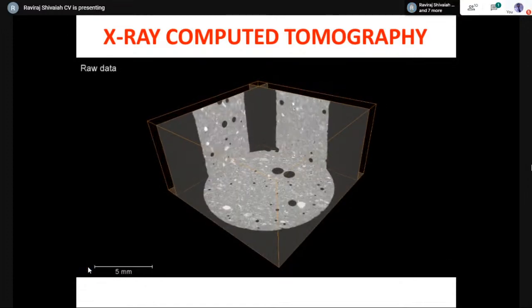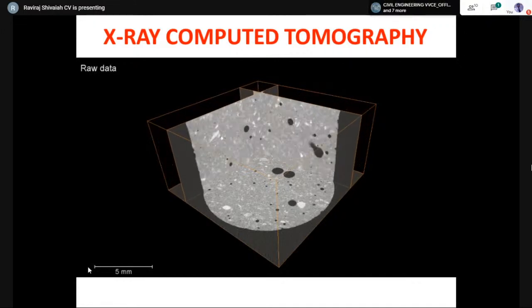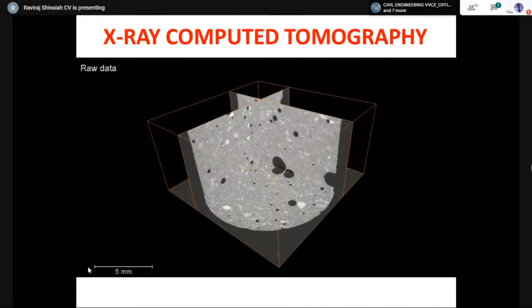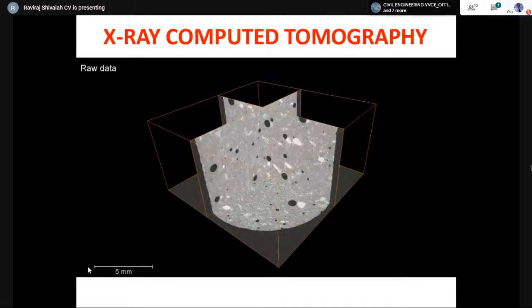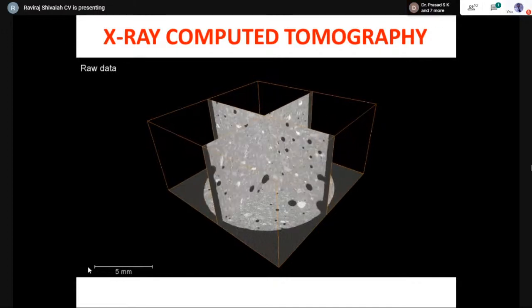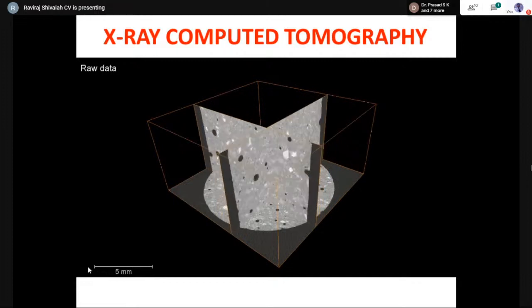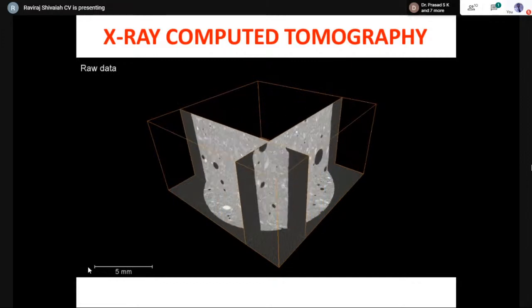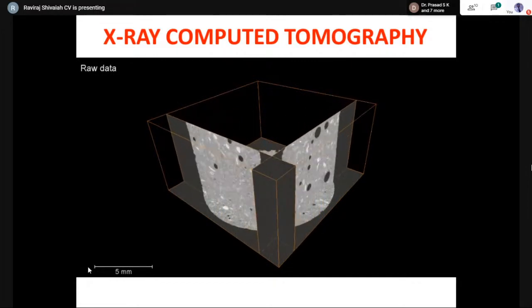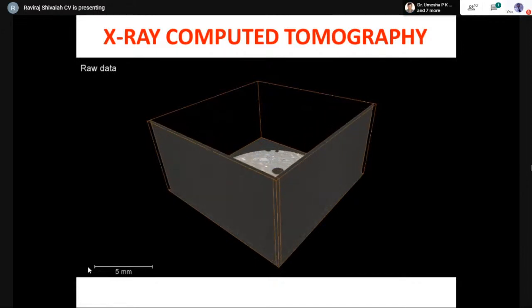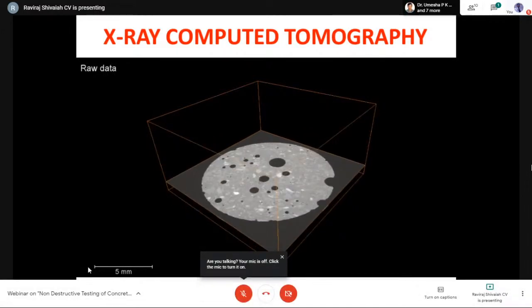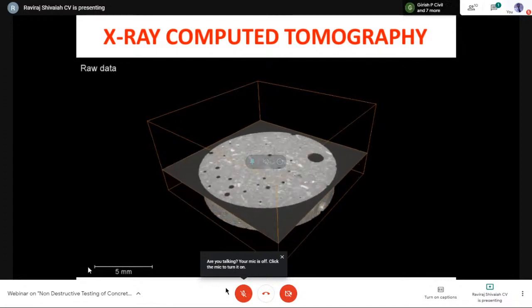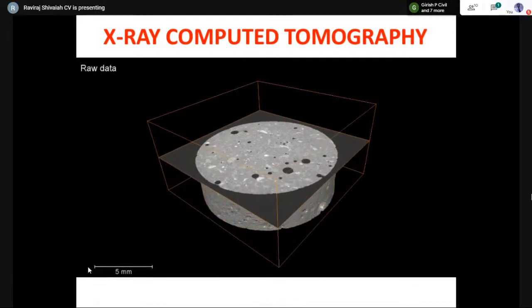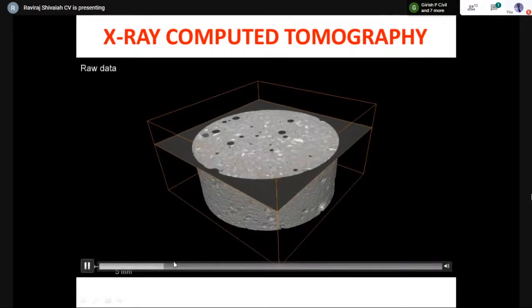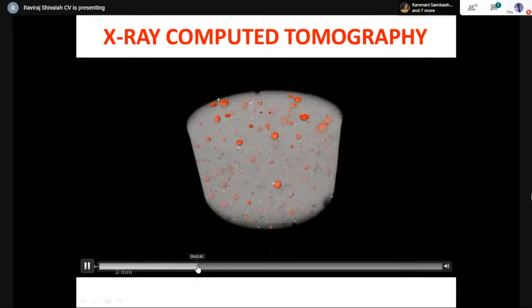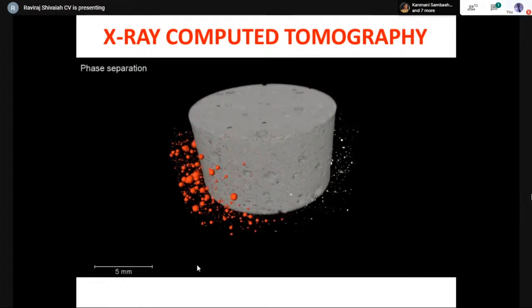So we have a simple concrete cylinder here where you are trying to move the slice in the X direction and Y direction, and you can clearly see the voids, the inclusions that we have, like the matrix, and the cement matrix and cement paste itself. So these are slices taken in X and Y direction. This is a slice taken in the Z direction. So those are the perpendicular directions. You can clearly see these kinds of things. It's very, very interesting. And it's also possible for you to have some kind of color coding.